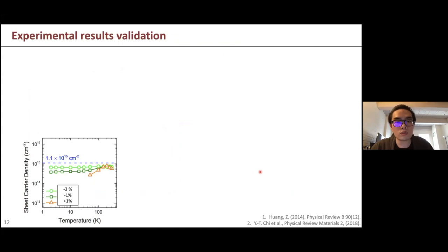So to validate the prediction, we found that another group in Singapore, not us, has done conductivity measurements of strained films in STO. This is basically the carrier density of a 0.5 weight percent doped niobium STO. So it has a fixed amount of electrons in this material. And then they grew the thin film on different substrates to create different in-plane strain. In this case, it is -3% compressive, -1% also compressive, and then +1% taking tension.